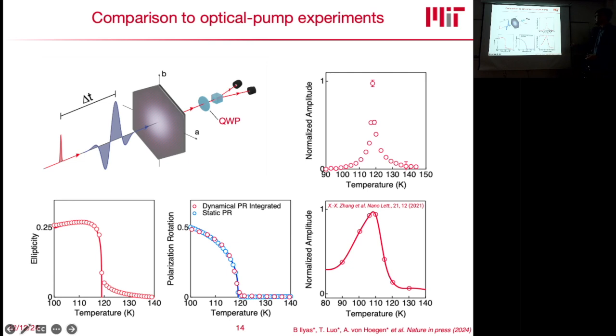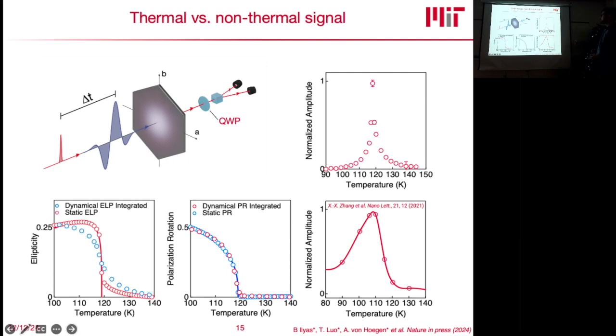So instead of this asymmetric shape, we now get this divergent shape, which is more or less symmetric around the critical temperature. And if you compare this now to the static ellipticity measurement, so you do this temperature integral here, you get something that's very different. So that already hints to us that there are non-thermal dynamics in the ellipticity measurements, and that what we capture with the polarization rotation is purely thermal dynamics in this long-lived state.